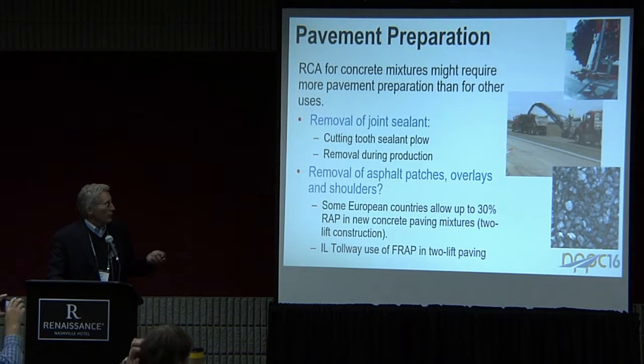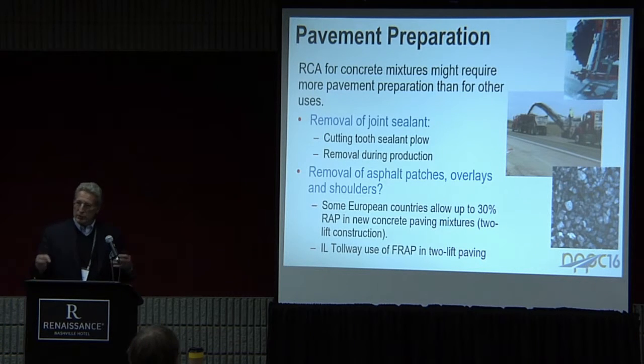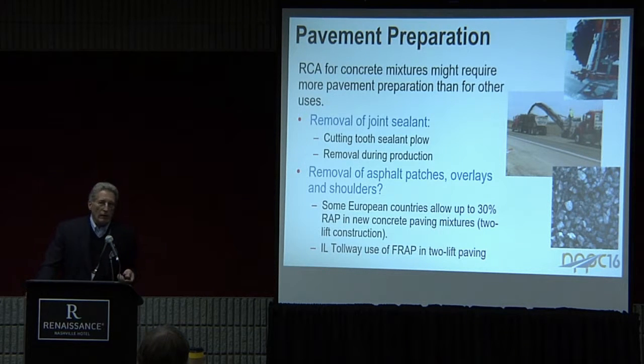Taking it out during the production process, simply beneficiating, removing that material after it's been crushed down. Removal of the asphalt patches and overlays and shoulders. Again, we used to require this routinely. Back in the 80s, Iowa did some concrete recycling back into concrete pavements, and they had allowed 30%, I think, asphalt to be recycled back in.